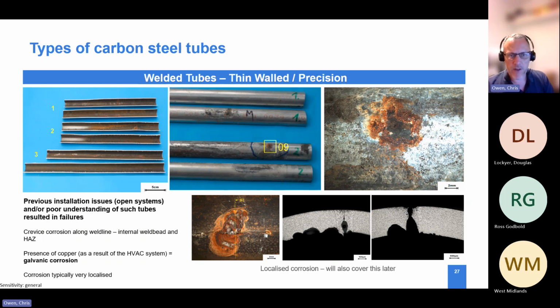But the problem we have here is, again, pipework which has been installed incorrectly, not maintained correctly, and not understood in terms of how some of these application conditions can impact it. What we saw is pinhole corrosion taking place as a result of galvanic corrosion reactions, and that caused a thinning of the wall in a localized area. And because this is thin wall material anyway, it obviously corroded and burst quite quickly compared to traditional tubes.